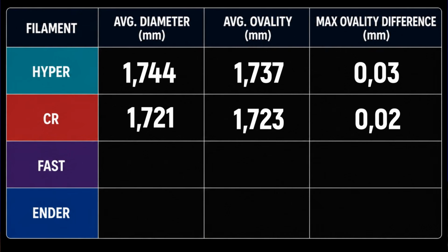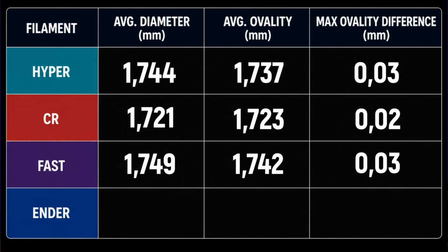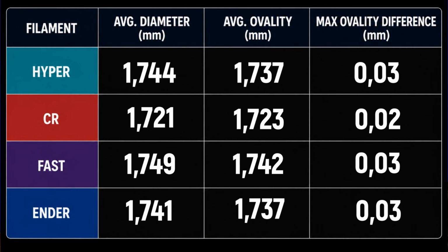The Enderfast's average diameter, which was the closest to 1.75, was 1.749 millimeters. Its ovality was 1.742 millimeters, and in the ovality calculation, the difference did not exceed 0.03 millimeters. When we moved on to Ender PLA, the average diameter was 1.741 millimeters, while its ovality was 1.737 millimeters, and again, the ovality difference did not exceed 0.03 millimeters.